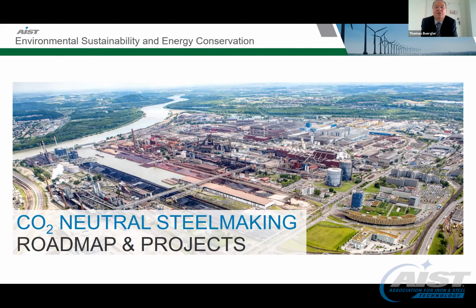It's a 6 million ton crude steel production here in Linz, a fully integrated plant with the coke oven plant from the left. Then you see the sintering and blast furnace area, the steel making, and the rolling and finishing lines in the south of the plant. And we have a second site in Donawitz in the mountains, in the Alps, and there we produce up to 1.8 million tons of crude steel. And in total, we produce in Austria between 7.5 to 7.8 million tons of crude steel.